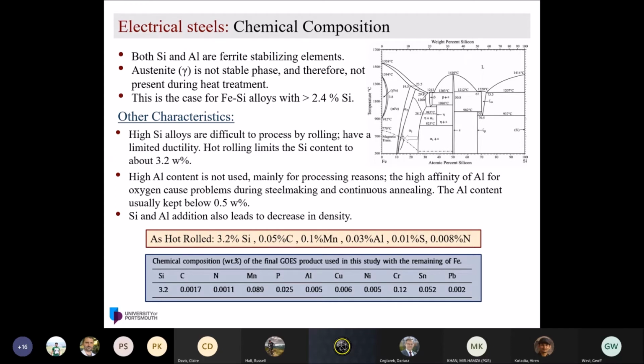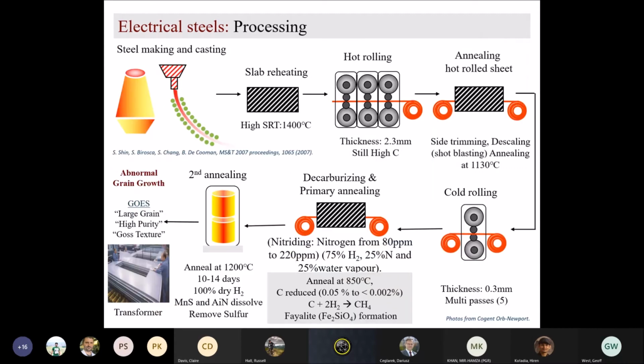Whenever they give you a chemical composition of silicon steel, it is always different at every single stage, coming from the thermomechanical processing and annealing. For example, if I look at the as hot rolled electrical steel chemical composition and compare it to the final product, you will see a huge reduction of carbon. In fact, the carbon should be absent, but we can't do that practically. That's why there are still some traces. Why the chemical composition is changing, I will show in the next slides, if you don't mind, Harry.